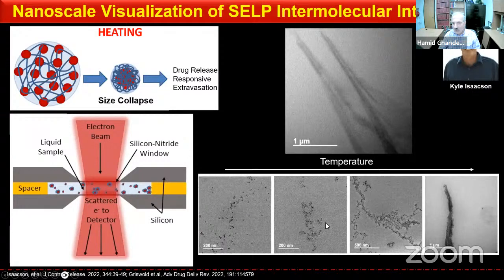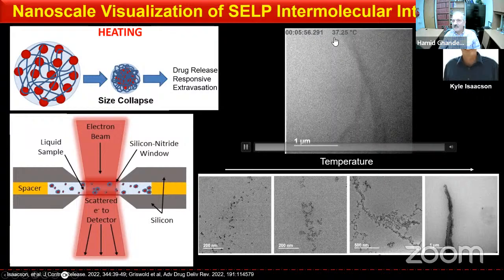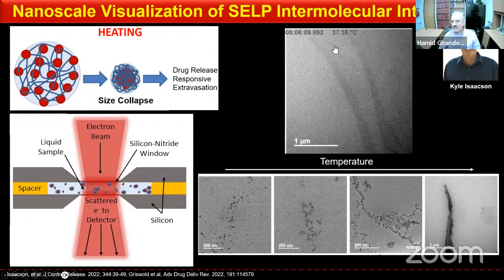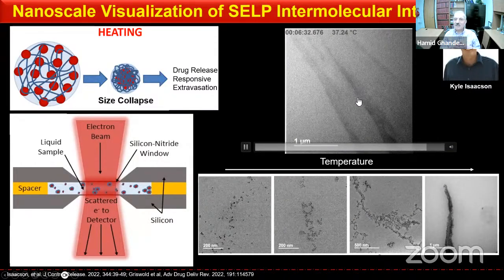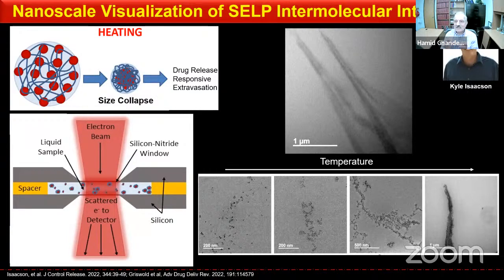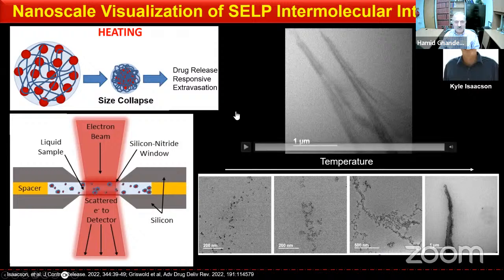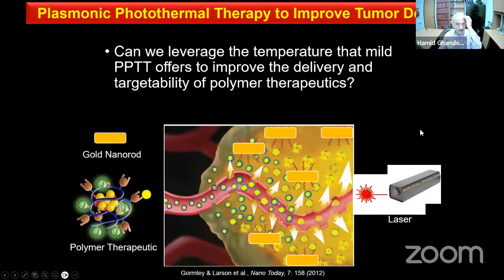One of my students made these nanoparticles from cells, but the challenge was that over a period of time, they would make fibers. You can clearly see in this video that at 37 degrees, even though we made nanoparticles at the beginning, later they start to make fibers. We hypothesize that the reason is that you still have silk units protruding from these nanoparticles that interact with silk units of other nanoparticles. Over a period of time, these polymer strands interact with each other and lead to the formation of nanofibers. So I'm going to switch gears from gels and nanoparticles to water-soluble polymers.